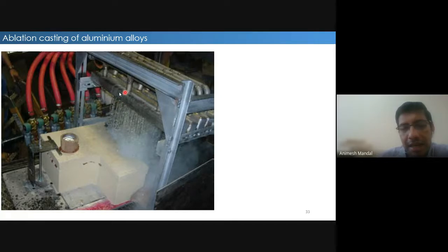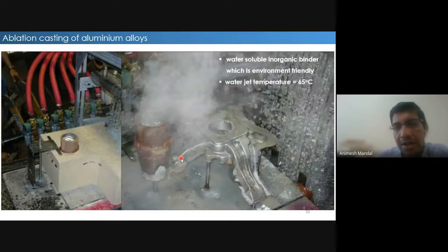This technique has lots of merits because you can achieve a very, very high cooling rate in this casting, which otherwise you do not achieve in a typical sand casting process. As a result, what you get is a very, very fine microstructure, which I'll be showing to you in the next slide.